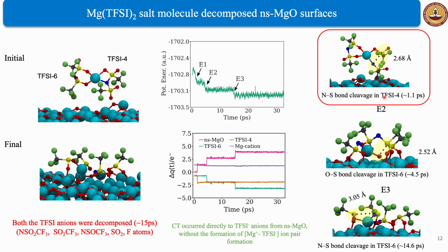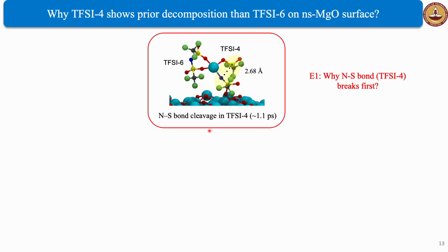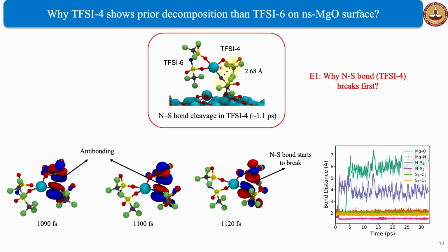Let's look at the first decomposition event in detail, which corresponds to the N-S bond cleavage in the TFSI 4-membered ring around 1.1 picoseconds. This preferential decomposition of the N-S bond in the TFSI 4-membered ring can be attributed to the localization of the LUMO over the TFSI 4-membered ring and the presence of anti-bonding character at the N-S bond.